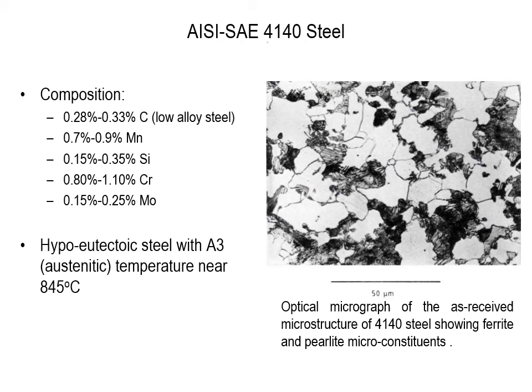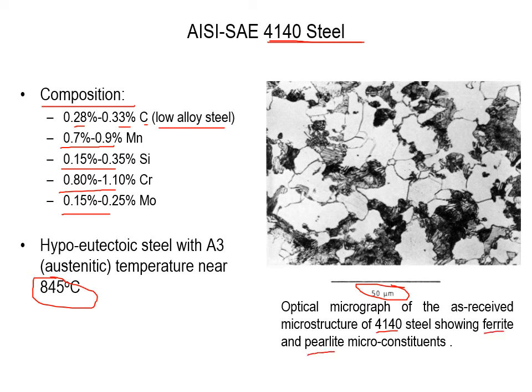Now, if we're talking about our 4140 steel here, we can see that for our composition we have between 0.28 and 0.33% carbon, so it's a low alloy steel. And we can see our other breakdown for the elements here as well for the whole composition. It's a hypoeutectic steel with A3 austenitic temperature near 845 degrees. So this is for our 4140 as compared to our 1080. We can see our micrograph over here. We have our scale of 50 microns. This is the as-received microstructure of our 4140 steel, showing again our ferrite and pearlite.